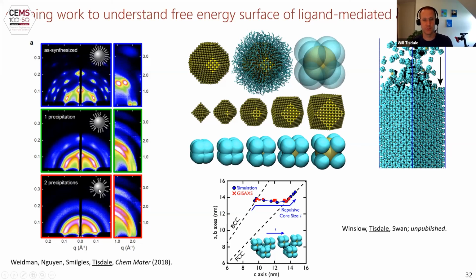As we do successive precipitations where we have lower and lower ligand coverage on the surface, eventually we don't get the formation of a superlattice at all. So you only get superlattice formation when you have a good coverage of ligand on the surface. That's the first thing I'll say. So the ligands are essential.